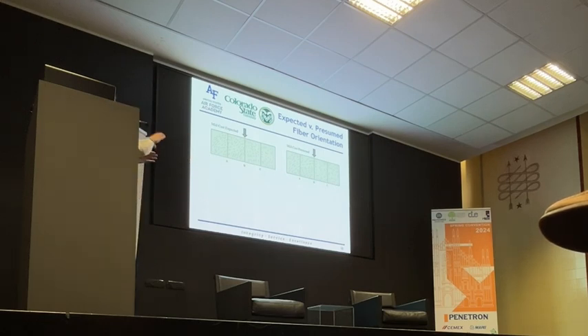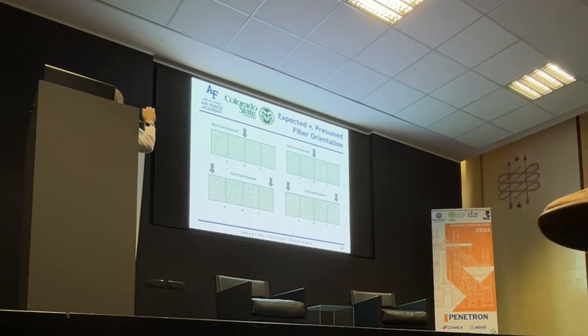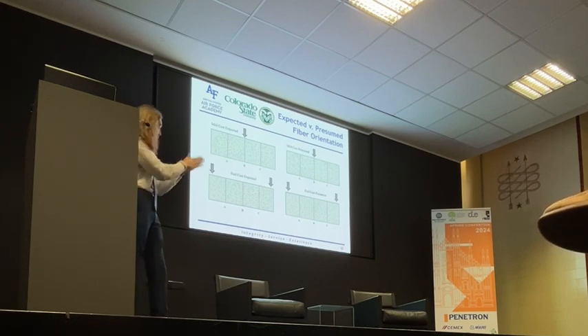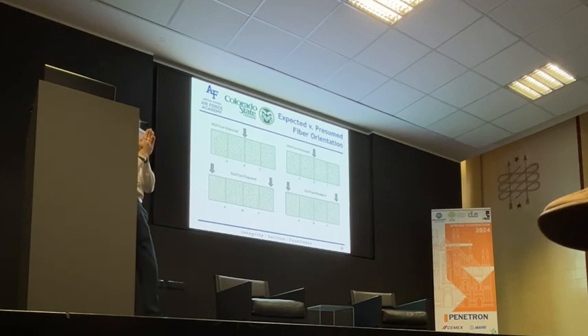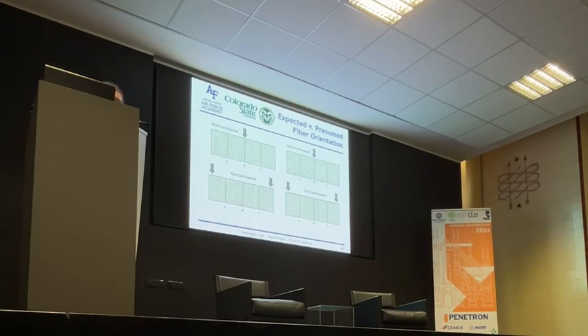We found that where we poured was more perpendicular, and where we didn't pour was less perpendicular to that transverse plane. So you'll find the exact same results when you pour at the end. We thought that it was going to be less perpendicular where we poured, but we found that where we poured is more perpendicular to that transverse plane than where we didn't. And with that, I'm going to hand it over to my colleague, Darcy Farrow.